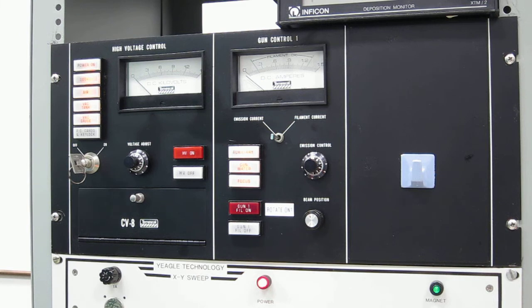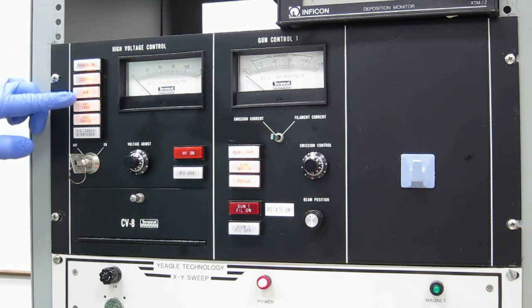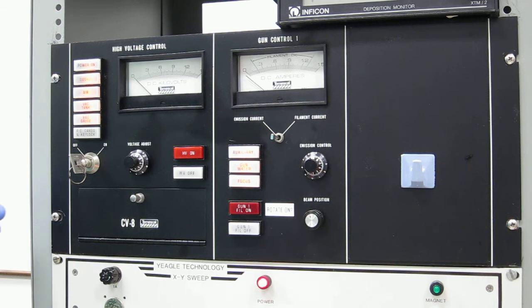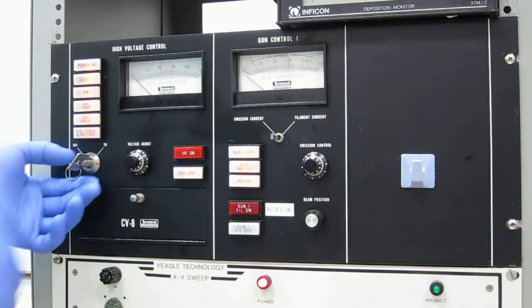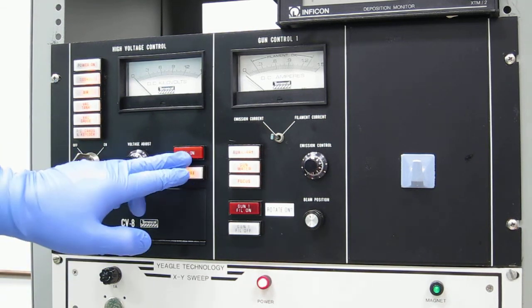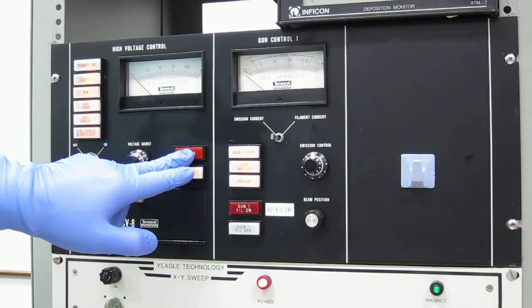The deposition system begins now with applying high voltage to the gun. Ensure that all of the interlocks are available, and that includes the airflow, the vacuum tank is actually down, and the vacuum gauge is interlocked to ensure that the vacuum is low enough for the system to start. Turn on the system and apply high voltage first.